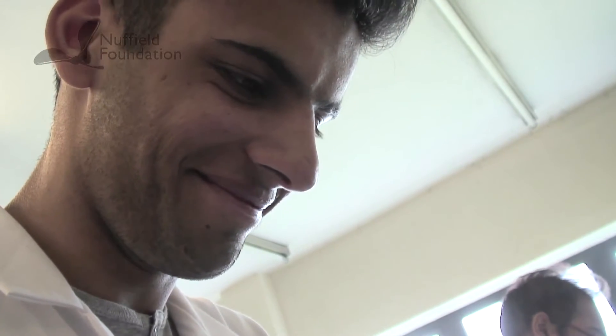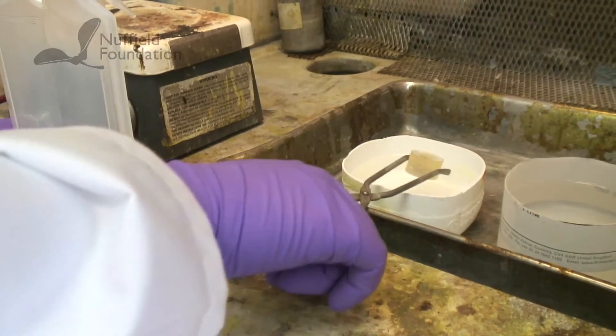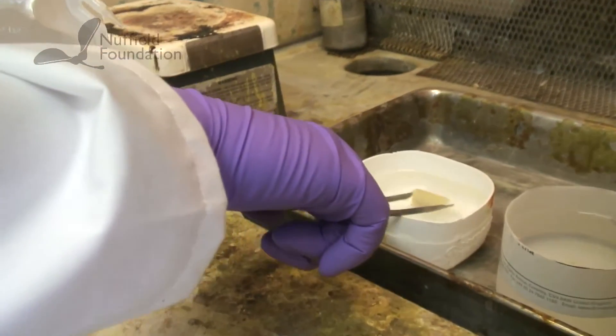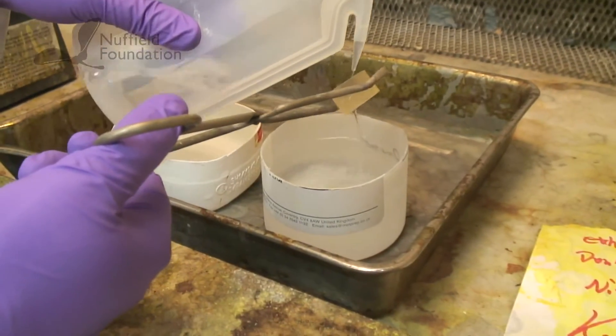I'm currently working with two PhD students. Half of the project so far has been grinding and polishing. And then we had to etch it in an acidic chemical which sort of attacks the grain boundaries to make the grains and the crystals in the metal visible.